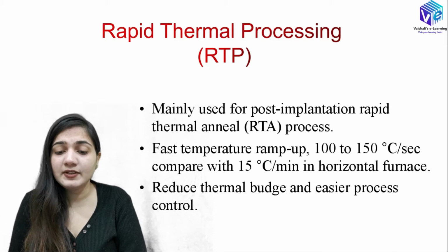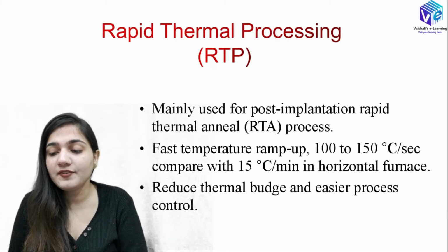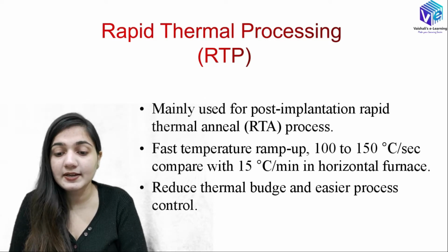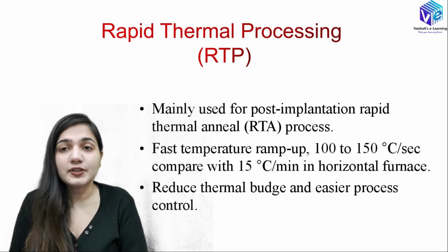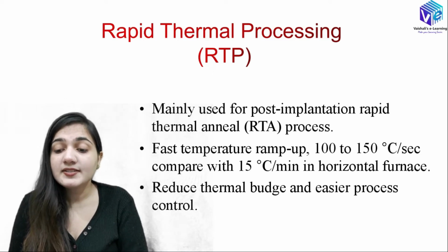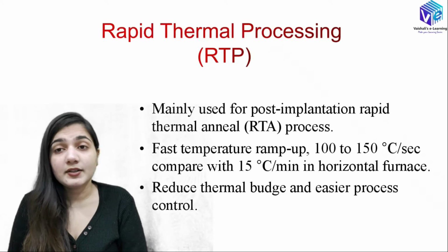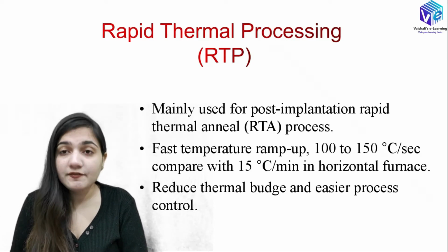Here we have a fast temperature ramp up, around 100 to 150 degrees Celsius per second. In the traditional horizontal furnace, we have 15 degrees Celsius per minute.